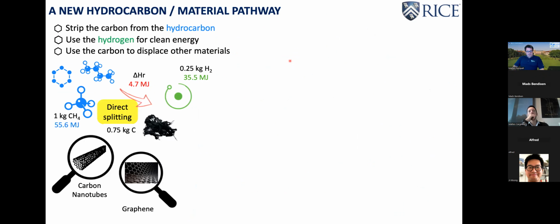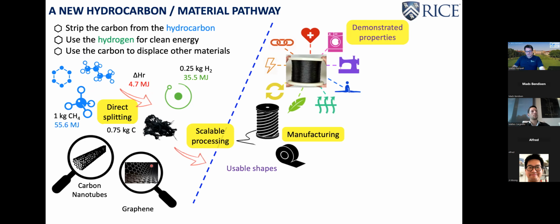So what would the pathway look like? Well, you can think about using lots of different hydrocarbons or even alcohols. The delta H of reaction is relatively small. Methane is one of the ones that has the highest delta H of reaction per kilo of feedstock. And if we could split it, we would get hydrogen and carbon. But what's very interesting, in the last 30 years, a new class of carbon has emerged based on carbon nanotubes and graphenes, and these are carbons that have structural integrity. So it's possible to take these molecules and make them into usable shapes with room temperature solution processing.